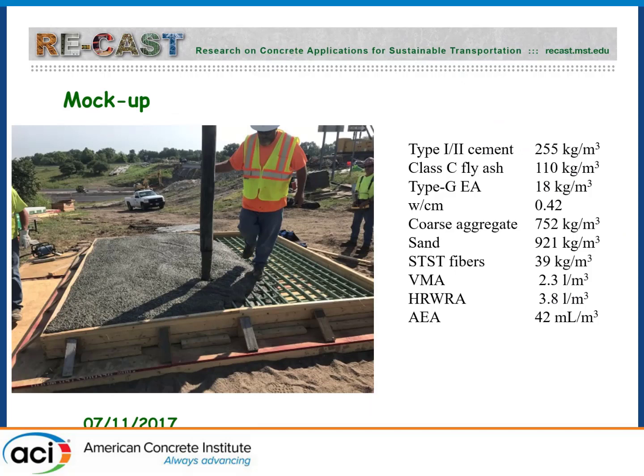And for the mock-up, this is a mixture. So you can see that a type 1-2 cement, 30% fly ash, some expansive agents, water to binder ratio 0.42, half-inch aggregates, river sand, and then the steel fibers, 80% macrofibers, 20% microfibers, and the 3 chemical admixtures. Not a very easy mixture to implement, but the concrete supplier got it right.